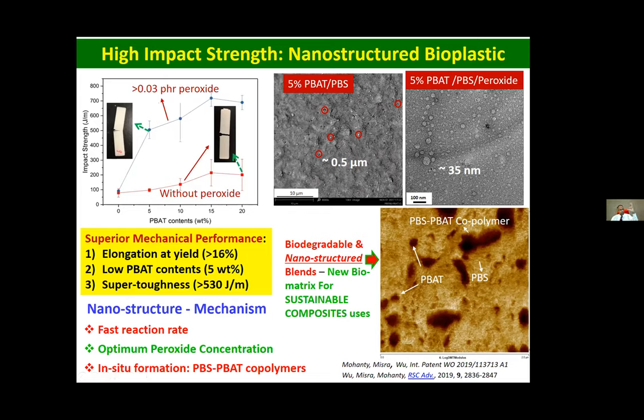But in the final product that you want to use for the real world application, you should have a stiffness-toughness balance. So what we do here, we use an additive in a very, very minute amount. This is a peroxide additive. By utilizing this peroxide additive, we could put a very small amount of a tougher polymer in the PBS matrix. So you can see in the AFM, atomic force microscopy, the PBAT, which is a very tough polymer, stays in the nanoscopic state in the whole PBS matrix. That is the beauty of these innovations.